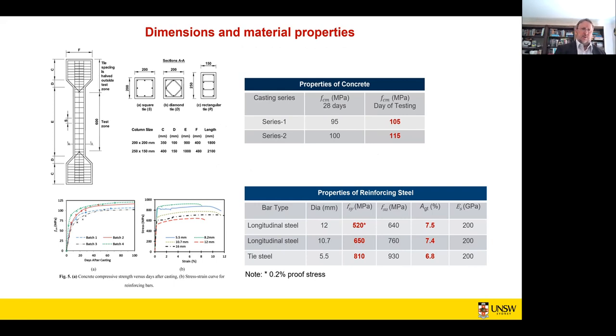Right. So we tested 39 columns of different sizes and different reinforcement arrangements. The concrete strength is here, it's about 110 megapascals. The reinforcing steel, as you see, is 520 megapascals for longitudinal steel, which is conventional. And then a 650 grade material, all tie steel was 810 megapascals, so it was a high strength steel.